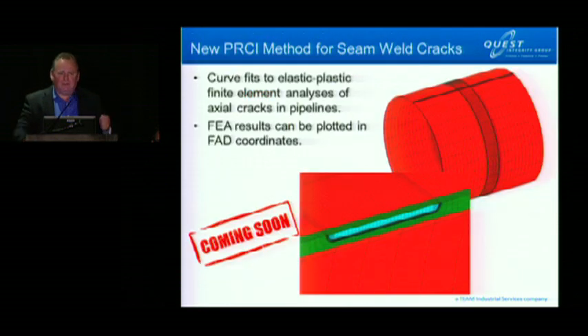Now, in addition to API 579, there's an alternative that's just coming off the assembly line, if you will, and that's some new PRCI research which we've completed, and we're currently finishing up the final report. It's a development of a new state-of-the-art crack assessment method, which actually leapfrogs the technology of what the rest of oil and gas is doing, and has the best available prediction model. And it's based on doing a couple hundred finite element runs of pipes with cracks, and then curve fitting them. So if you're a member of PRCI, the draft report should be up on their website within a couple of weeks.